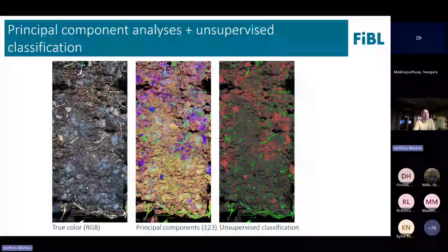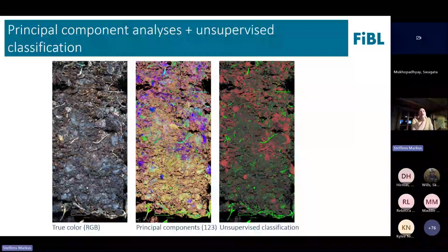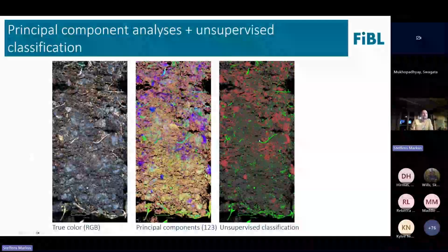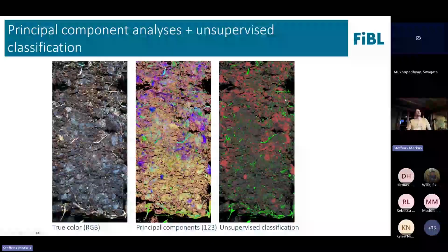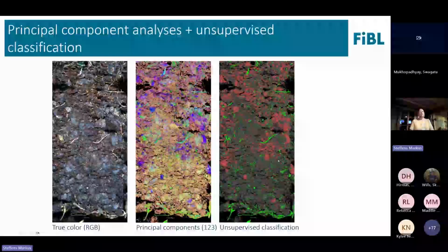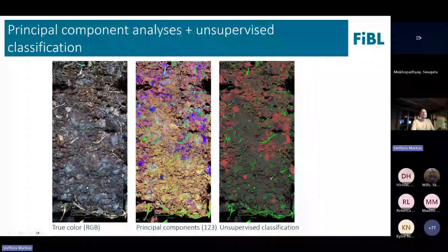And then we did unsupervised classifications, and we got this result. So that's not supervised, but unsupervised, just based on the variability of the spectra. And from the first indication, it looks good. So we have, for example, this fresh root. It's green, and everything in bright green, that's living or very fresh organic matter. And then we have 2 different other compartments.